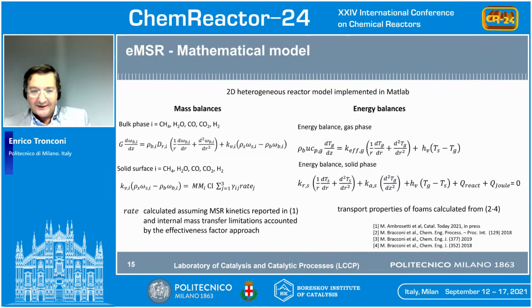In parallel to our experimental activities, we have run also modeling work. We have developed a simple two-dimensional heterogeneous reactor model of our electrified steam reformer. We have used rate expressions derived from our recent kinetic investigation of methane steam reforming over the same rhodium-based catalyst tested under concentrated conditions. And for the estimation of the heat and mass transfer coefficients, on the other hand, we have used the engineering correlations that we have derived during our previous fundamental study of the transport properties of open cell foams as enhanced catalyst carriers.